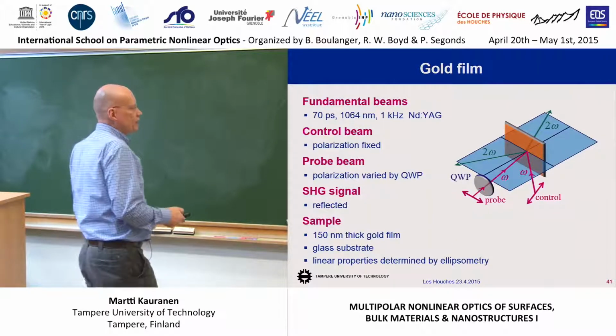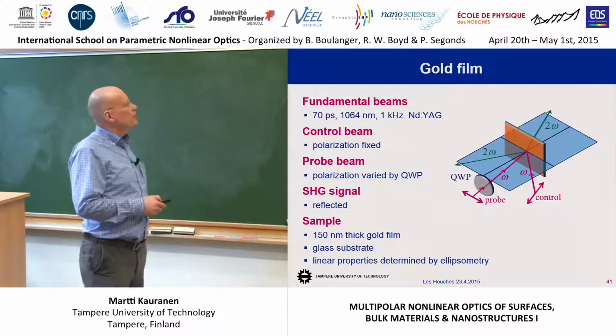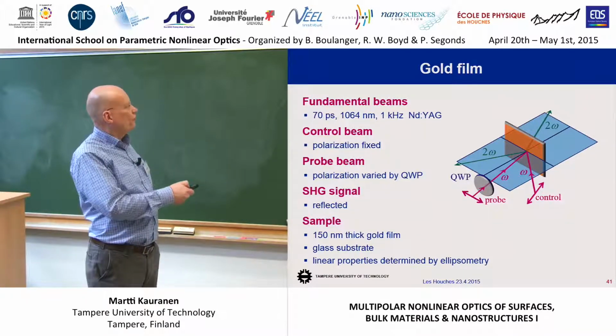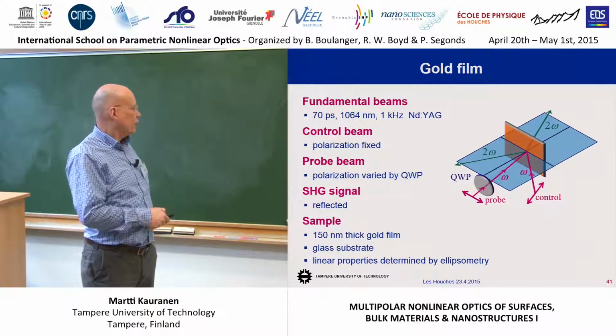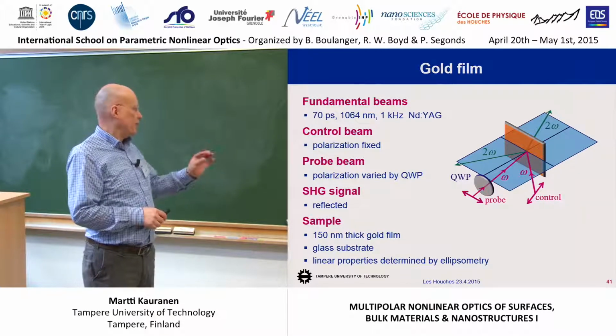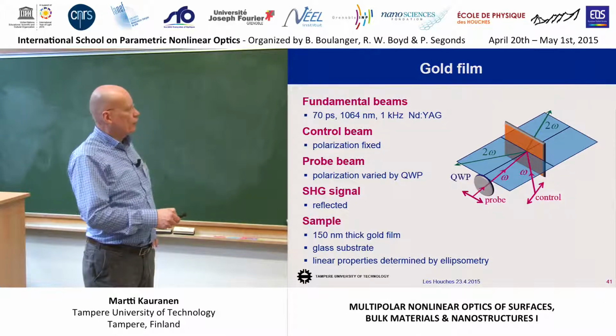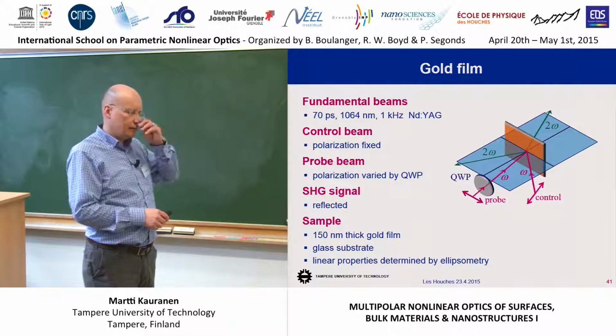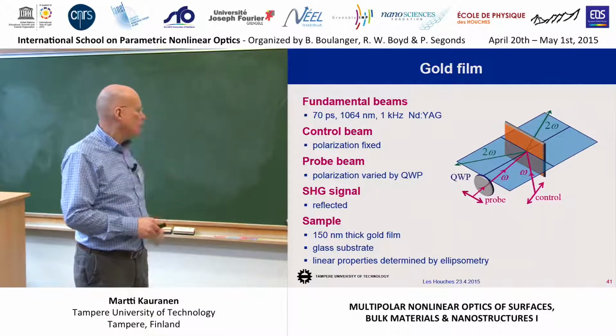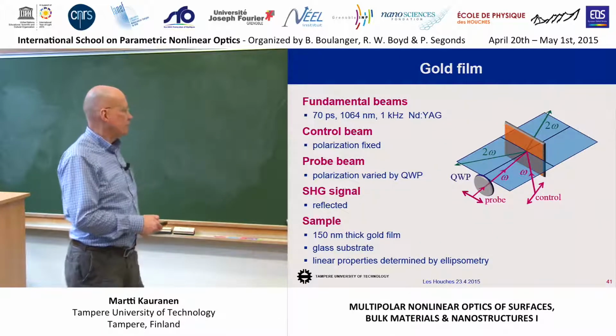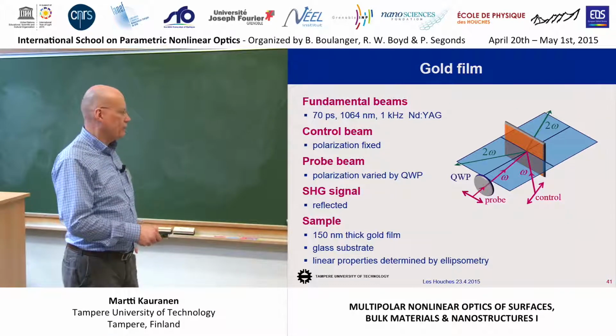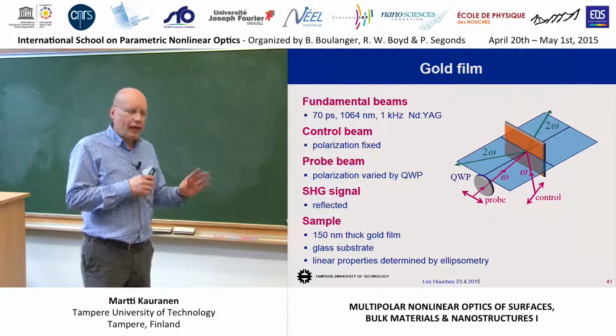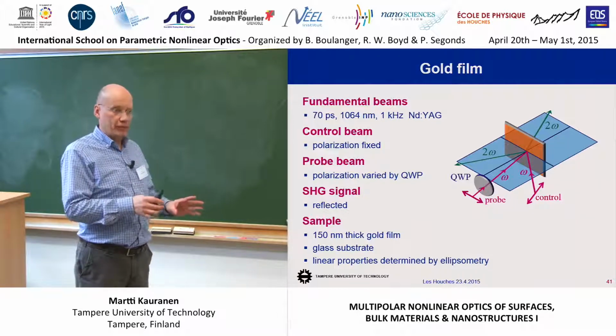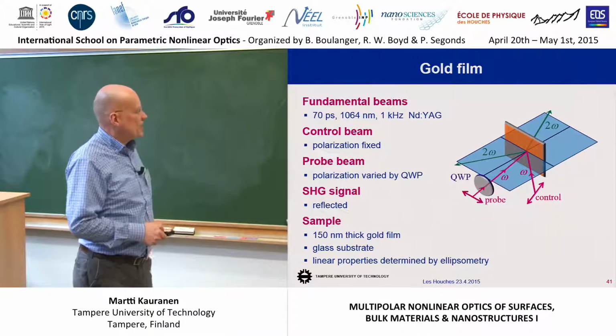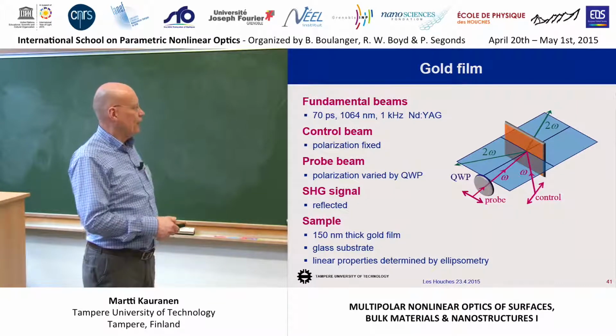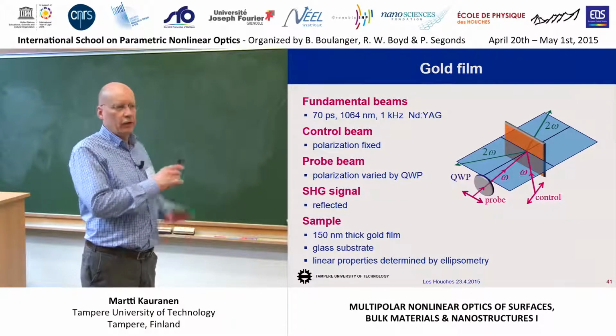So the same experiment, two-beam experiment, but now using a gold film, thickness of 150 nanometers, so much thicker than the skin depth. So we are not actually even reaching the back surface or interface of the film. It was on the glass substrate. We measured the linear properties by ellipsometry in order to be able to make as precise modeling as possible, which is actually important. But otherwise, the same experimental setup: control beam, probe beam, polarization modulation, measuring a lot of stuff, and so on.